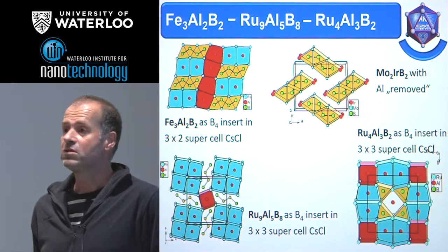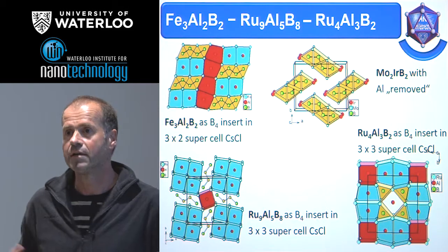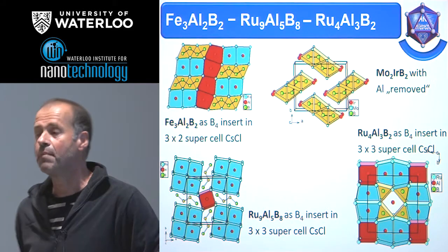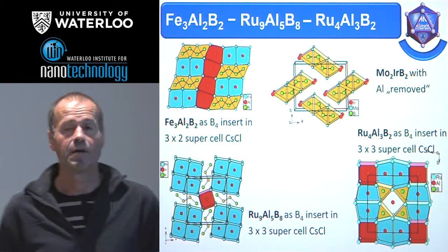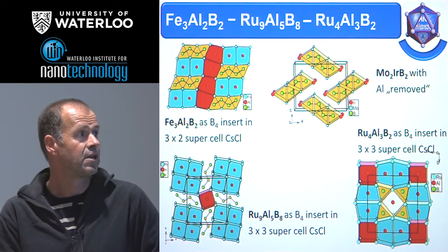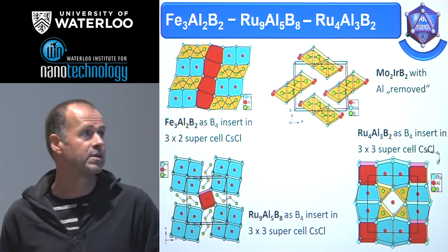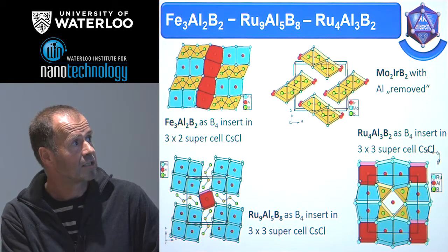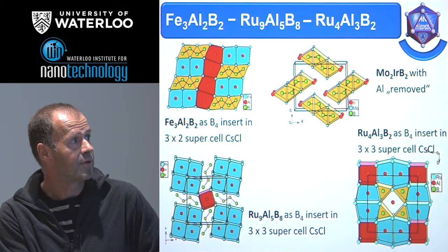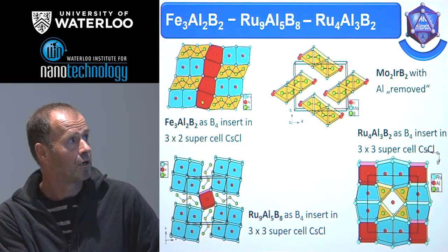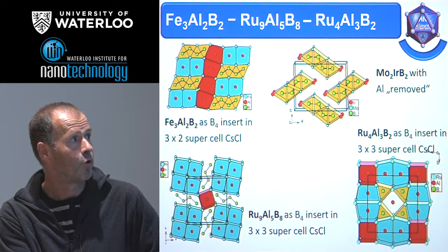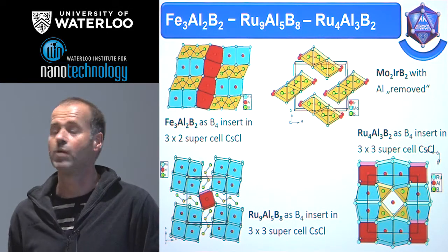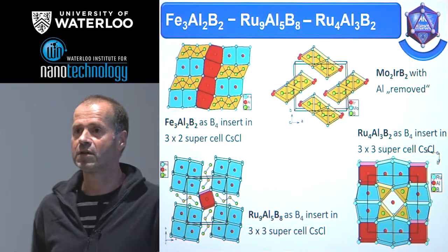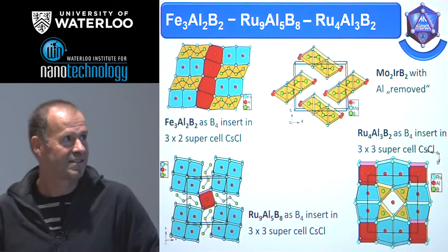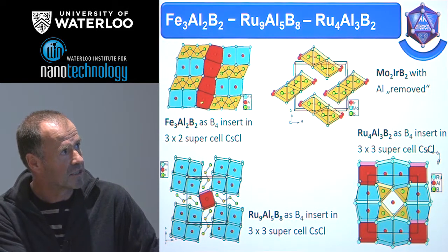Well, that's one idea to explain the crystal structure. Another idea is to remember that many intermetallics have a BCC, or if an ordered variant, cesium chloride structure. And that's another way to explain this new structure. We can start from a cesium chloride type as a 3×2 supercell and substitute 2 of these cubes by 4 of the boron atoms. And it works quite well, and because trigonal prisms are no squares, you have to do a little fitting, so it's a little bit distorted, but nevertheless